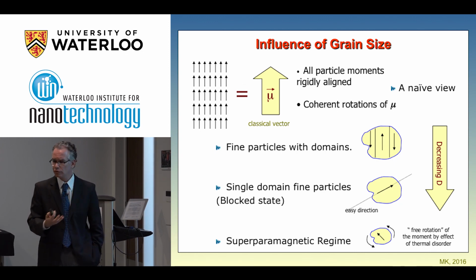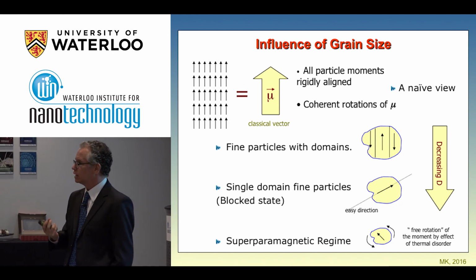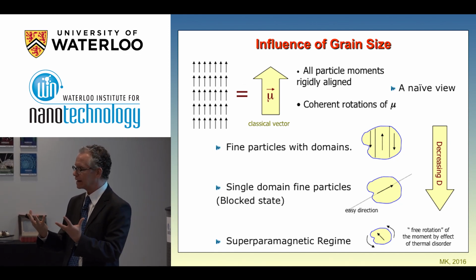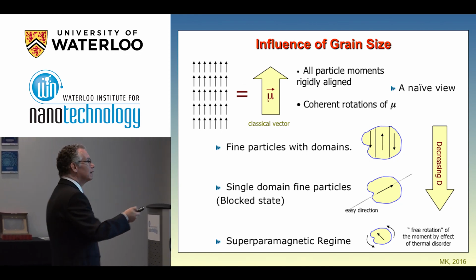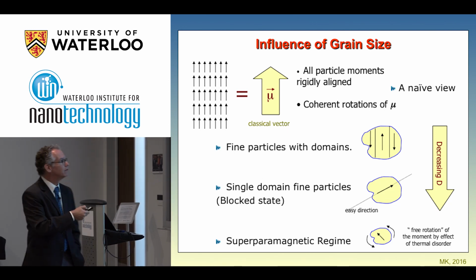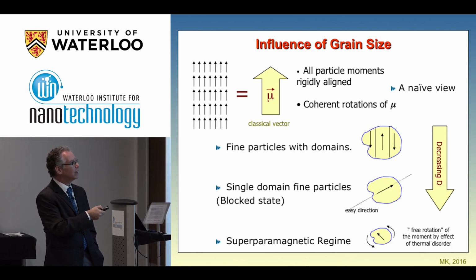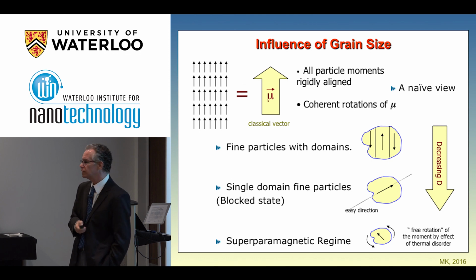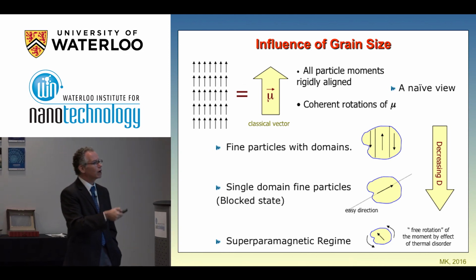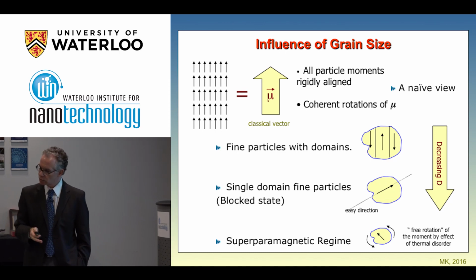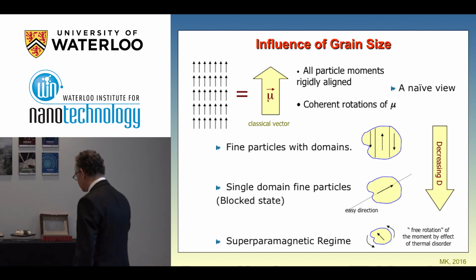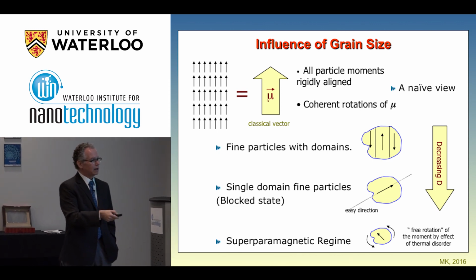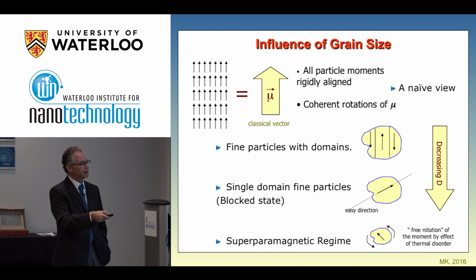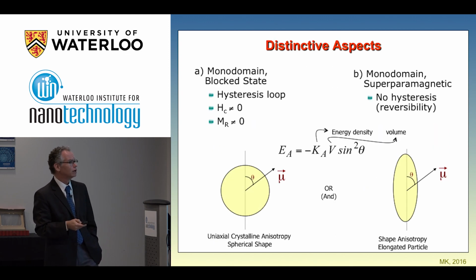model this problem. Although the magnetic system or the magnetic materials are essentially quantum in nature, because the magnetic interaction is quantum, you can treat the system as a classical vector if you consider all the spins in the system coherently oriented and coherently rotating. So they are rigidly aligned, and you can consider this as a huge magnetic moment which rotates freely. So you can make a very complete and rather correct classical approximation, and you can have this super spin rotating freely. And this is what's called the superparamagnetic regime.